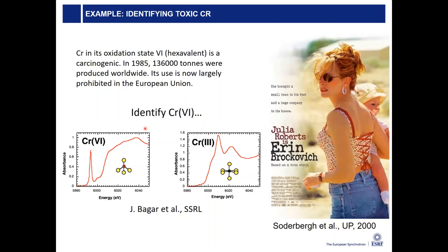dumped a lot of chromium 6 into the environment, and you wonder, how can I find out whether a piece of soil has chromium 6 or chromium 3? And the answer is, you measure the absorption spectrum. You see here clearly, this is the K absorption edge of chromium. If you have chromium 6, you see this strong line here, this pre-edge peak coming up. If you have chromium 3, you don't see it.